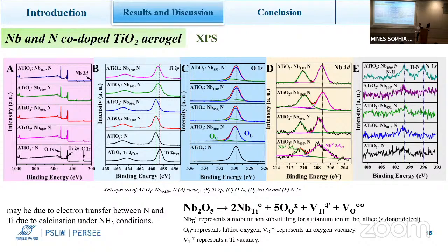The first one, you use urea. It's the same as with copper: at the gel synthesis, we already added the urea in the gel. So during the calcination, it's going to decompose, the organic and oxygen stuff is going to be burned out, and the nitrogen is going to stay in the lattice. Okay, so that means all the characterization is done after calcination. Yes. Okay, but sometimes it's not so clear.